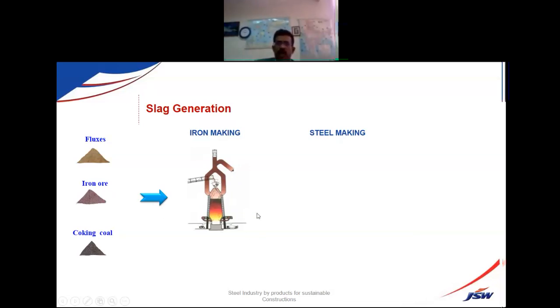Then, for every ton of hot metal we make, we get about 250 to 300 kgs of slag, which is the byproduct. This byproduct is taken out and quenched using chilling water into granules. This is a highly mineral rich product which can be utilized to make various products.